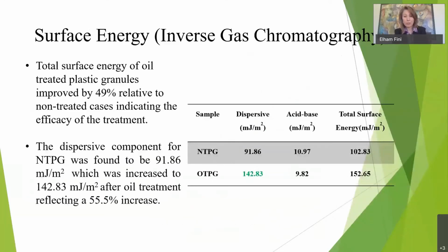And one other characteristic that was very important was the surface property of these granules. As I mentioned, plastic itself doesn't like construction material, doesn't like cement or asphalt. In this case, we actually changed the surface energy. You can see from 91 before treatment, this is the neat sample, to 142 after treatment. So this 55% increase in the surface energy, in the dispersive forces, shows the interaction would be enhanced when we mix it with other construction material.